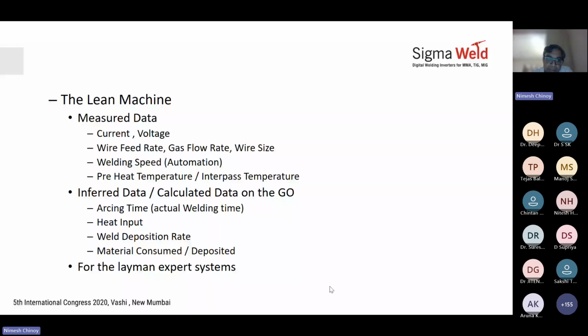and you can have longer welds. What is the weld deposition rate? How many kgs per hour were you able to deposit the material? And what is the material consumed versus deposited? That means if you welded for 4 hours, did you deposit 2.4 kgs? You deposited 3 kgs. How much material did you consume? You can calculate that on the basis of the measured data. And for the layman, this can act as an expert system. So if somebody doesn't know how to calculate heat input, this could give you the inferred data directly.